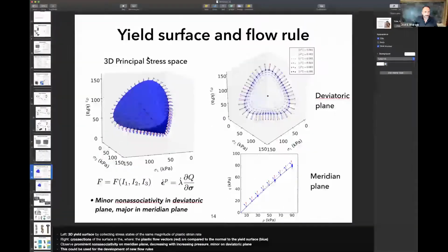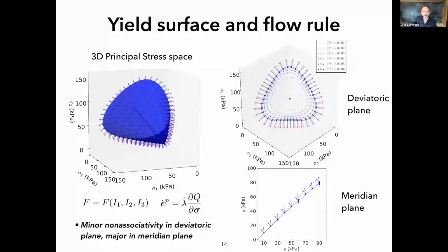Just before we do that, you can then get your good old yield surfaces that you like to have in your plasticity models, right? So again, you see that from all of this, you get the beautiful shape that you would expect, right? That sort of triangular shape in the deviatoric plane. We also discovered that as plasticity evolves, that shape goes from something that looks more circular to something that looks more triangular. There is definitely non-coaxiality,